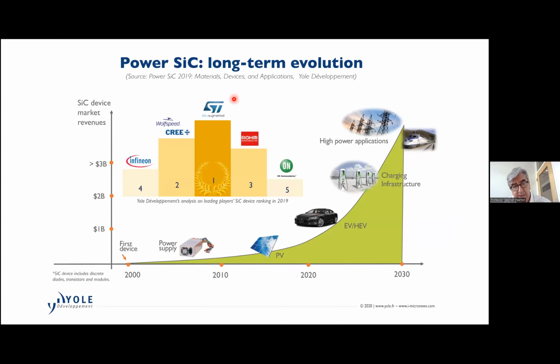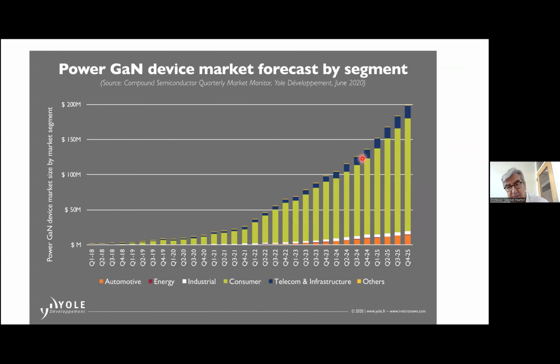So in fact, if you look at the projected market for silicon carbide device revenues, this comes from Yole Développement. I caution you a little bit. I'm so old, I've been looking at these kinds of plots for 40 years now, but it always seems like 5 years beyond the current, the thing just takes off into the blue space. But there is some reason, there are some facts behind that. So in this case, the electric vehicle and charging infrastructures and the switching of renewables should lead to a bright future for silicon carbide. Similar thing for gallium nitride. The revenues are expected to go up. Still a tiny market compared to silicon, obviously, which is around 400 billion, but still playing a very important role.